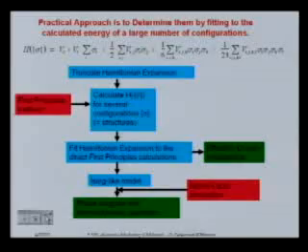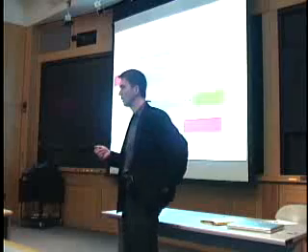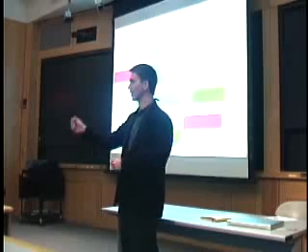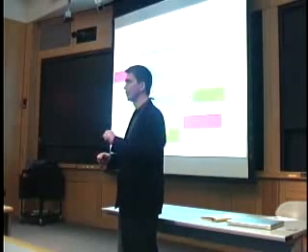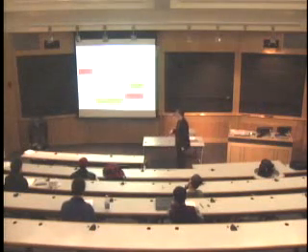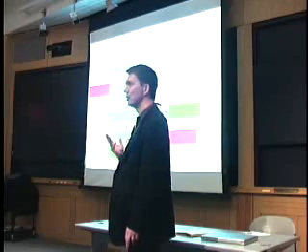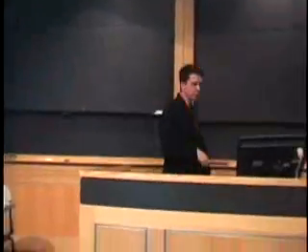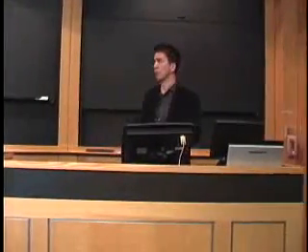There are people who do it numerically, very much according to the definition. You literally take a system, put an A atom here, and then calculate a lot of different configurations around that, and so start to approximate those averages, E_A averaged, E_B averaged. The practical way people pretty much do it now most of the time, which is also the least elegant way, is that you fit your whole expansion at once to a large number of energy calculations.